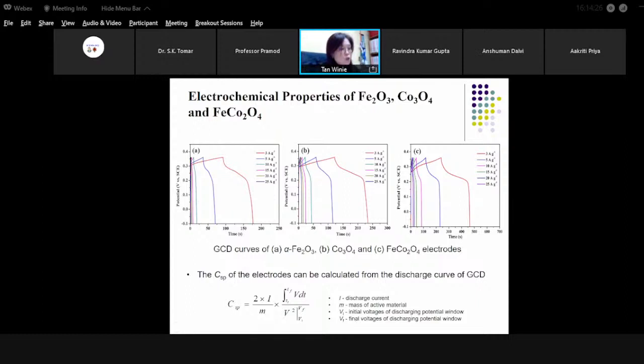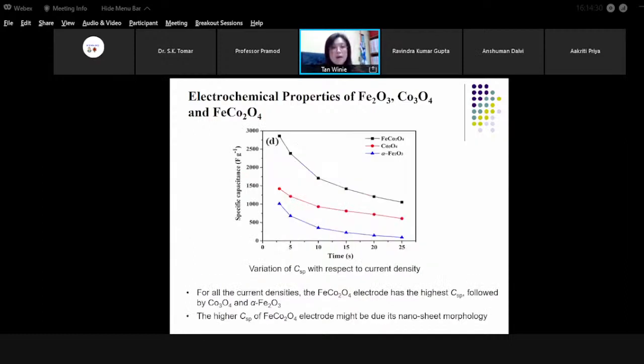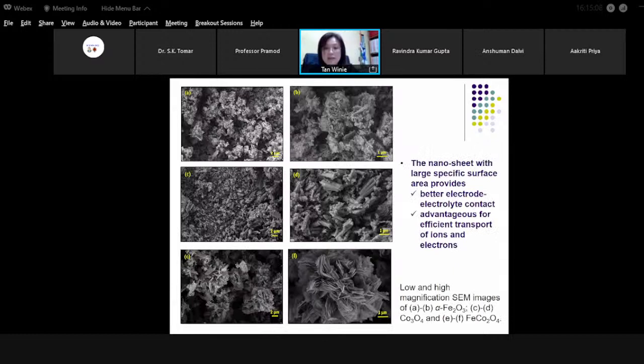So the most important thing here is we calculate the specific capacitance. Here we can see the variation of the specific capacitance with respect to current density for these three materials. You see, for all the current densities, the iron cobaltite electrode has the highest specific capacitance, followed by the cobalt oxide and also the hematite. The higher specific capacitance of the iron cobalt oxide might also be due to its nanosheet morphology that I captured using the FESEM images. I will talk about this in more detail in my following presentation.